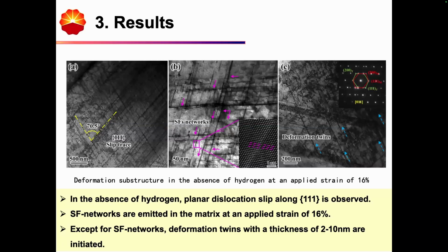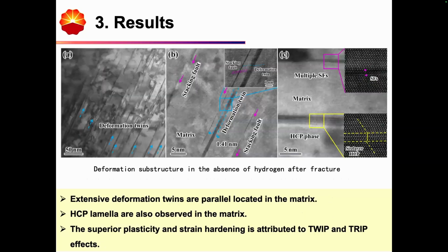If we enlarge the regions, we can see some stacking fault networks have formed. Besides the stacking fault networks, we also observed some deformation twins, but the number density is lower.